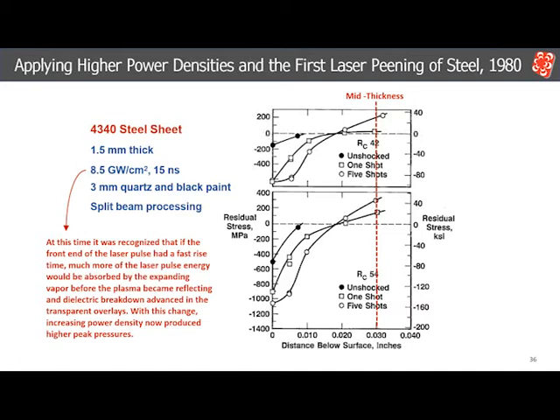The surface compressive stress in RC54 steel was about the same for 1 shot and 5 shots, but in depth 5 shots produced higher stress. Because of the thinness of the sheet, more shots could not increase the depth. The zero crossing was the same for both 1 and 5 shots.